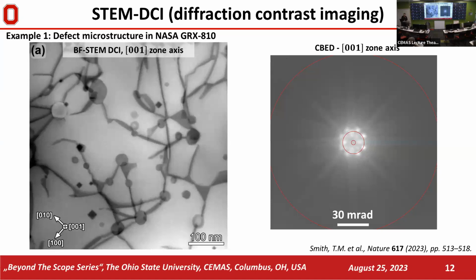The producer of the probe-corrected system usually advertises the system as state-of-the-art atomic resolution, a few tens of picometers resolution, but we use these systems for large field of view diffraction contrast imaging to obtain information about the microstructure.